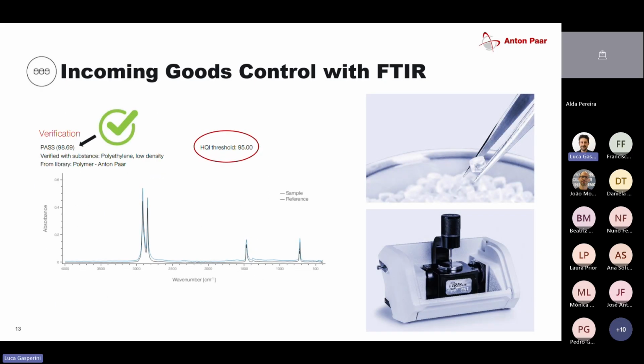So we said I brought two spectra with me. The black one is the reference, which is the gold standard, and then I have a sample, which is the blue spectrum. And as you can see, these match very, very well with each other. So I'm doing incoming goods inspection. I said I want to have at least 95%, like a hit, like it should be 95% the same sample, and the instrument now checked, and we got a fit of almost 99%. So we are within spec, so it's the same sample more or less.